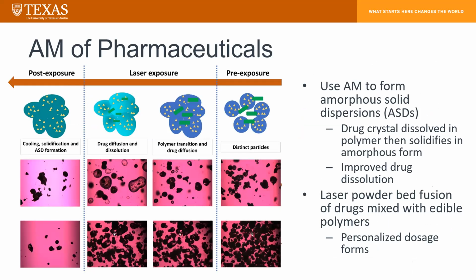Another application we're working on is additive manufacturing of pharmaceuticals. So to do this, we take a pharmaceutical drug and mix it with an edible polymer and use laser powder bed fusion to create personalized dosage forms. And when we do this, we're actually creating what's known as an amorphous solid dispersion, or ASD. What that means is that when we process this material with a laser, we melt the polymer, and the crystalline drug actually dissolves into that liquid polymer and gets locked in its amorphous state. And the amorphous state of this drug has orders of magnitude higher water solubility than the normal crystalline state. And so that means it has much more availability within your body, and it's a higher performance drug.